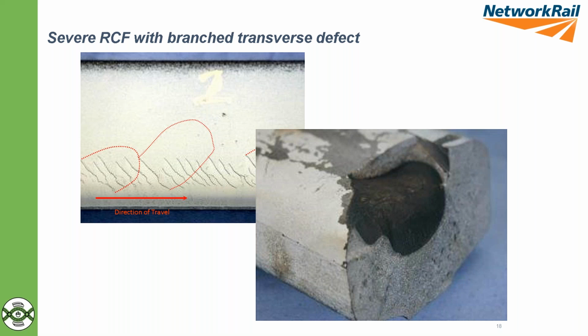And you can see the transverse defect that started at the surface, propagated some way down into the rail to about 5 or 6 millimeters deep, then branched and turned into a transverse defect, which this one fortunately didn't result in a broken rail. This sample we broke open, but it shows the extent of growth of cracking that can occur from something that perhaps on the surface doesn't look quite so serious, and that's one of the sort of challenges. But certainly RCF's not something that's gone away. It's still growing in smaller volumes when you look at it year on year, and it's something certainly from my sort of radar and headline, we need to make sure this doesn't creep up on us, that we end up with an unsustainable amount of re-railing, and similar, we find more effective ways of controlling it.